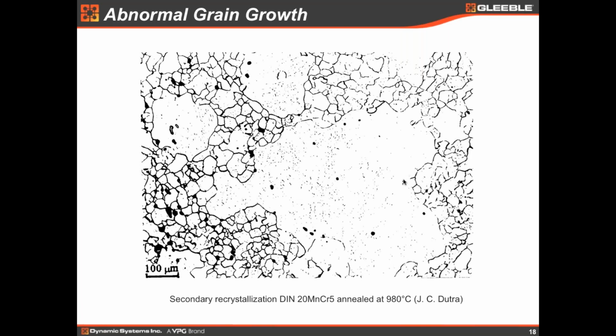Now this is a picture of abnormal grain growth, and this should be avoided in, let's say, engineering materials, because it reduces drastically the toughness of the steel or of the metal. So if you have these big differences in grain sizes, these abnormal grains and normal grains here, there's a very deleterious effect on mechanical properties.